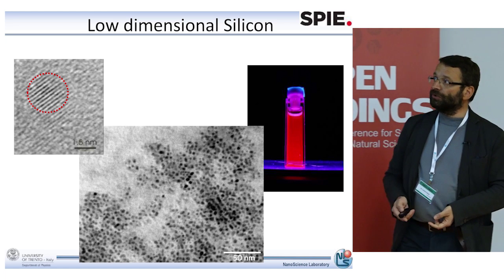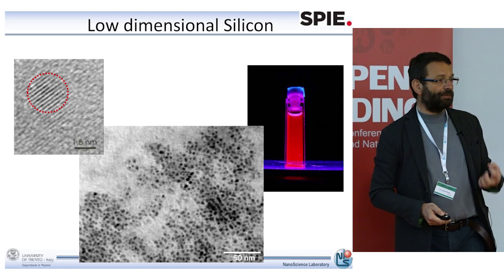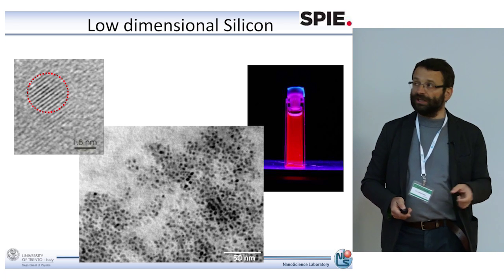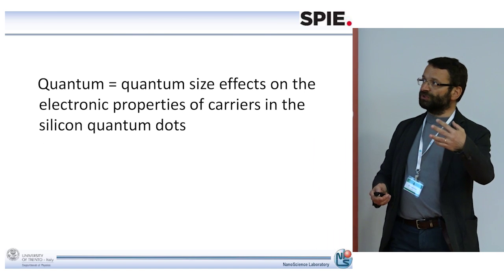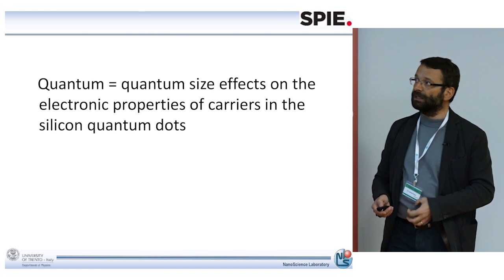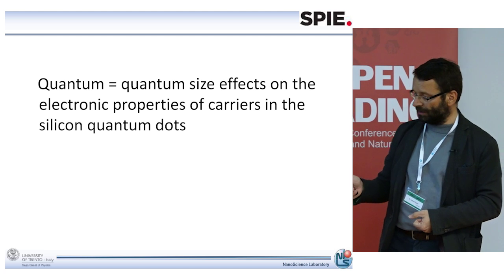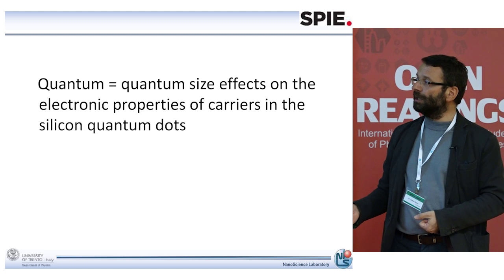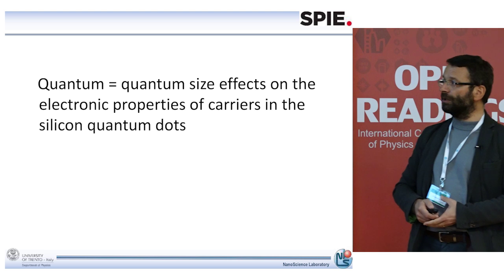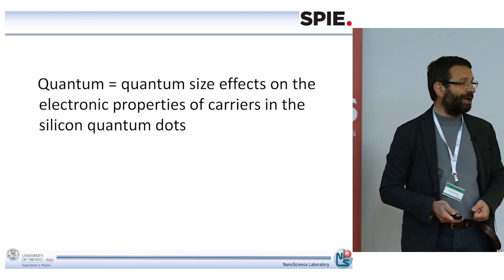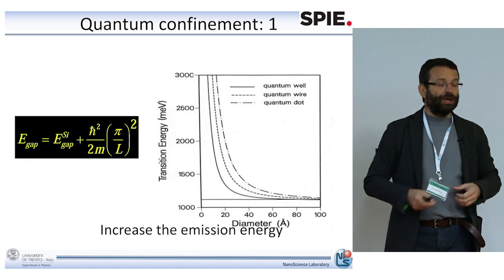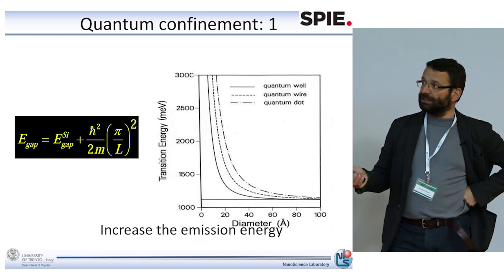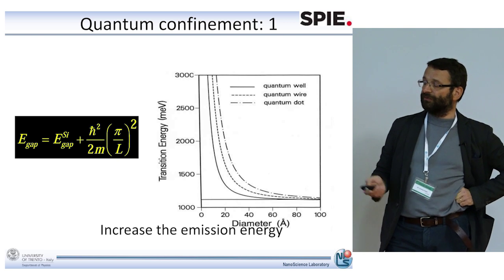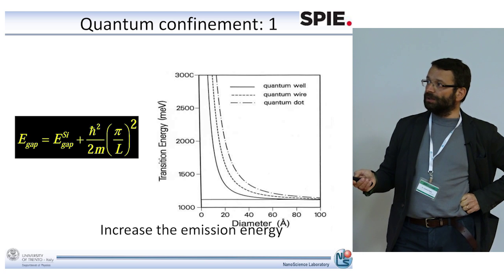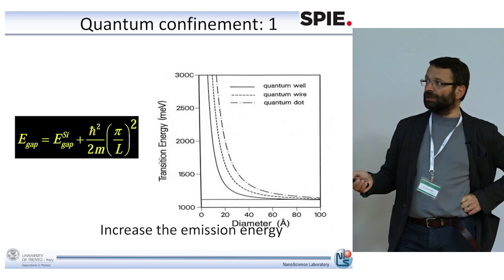And so here you see that by using these nanocrystals, it's possible to push silicon into the quantum size effect, and so you drastically change the electronic properties of the carriers in those silicon quantum dots. The first one is quantum confinement, so you reduce the size of silicon, and as a consequence, you increase the band gap of the material. And here is a plot of the transition energy, so the fundamental band gap, as a function of the diameter of the nanocrystal.